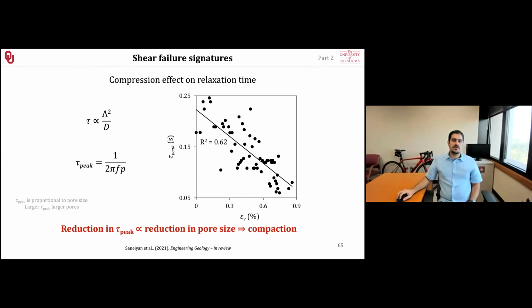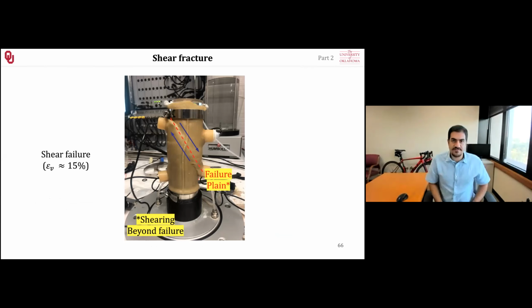So our imaginary conductivity and phase shift, and basically the complex conductivity, was capable of showing the soil failure. The soil failure clearly occurred in our samples. I pushed this far beyond its failure point. You can clearly see the fracture inside the column. Our initial failure occurred at a much smaller value than this one that you can see in here. But just to visualize it, you can clearly see the same kind of fracture I showed you initially. Schematically.